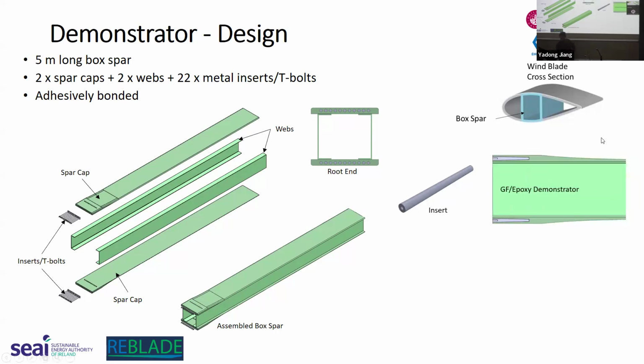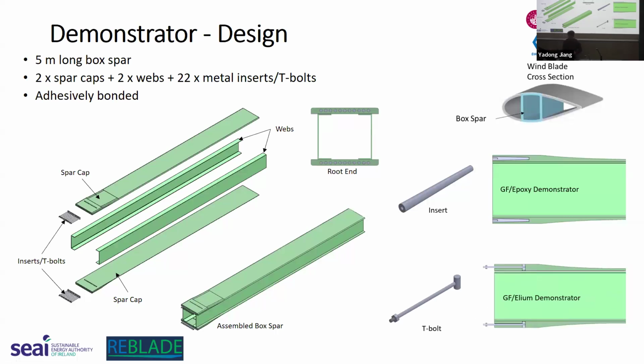And then on the side here we have the glass fiber epoxy demonstrator, a section view, and we also have the glass fiber Elium demonstrator, a section view of those. The geometry and all the components are the same, except the metal inserts or the T-bolts. This one is a carrot-shaped insert, and it has a tapered design. So there's a larger diameter at one end and then a smaller diameter at the other. So you have to have a machined tapered hole, and then an allowance for a bond line to bond those inserts in after the component is manufactured.